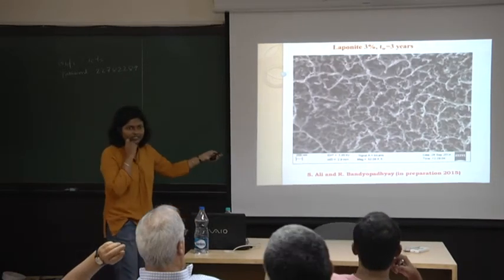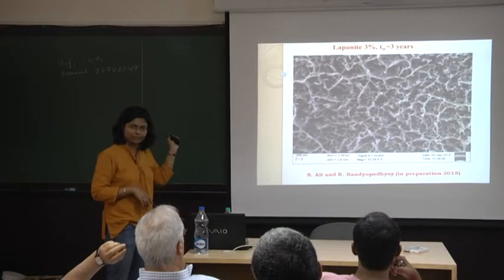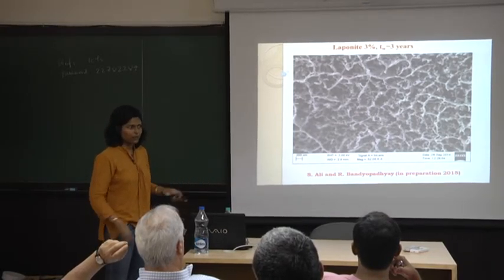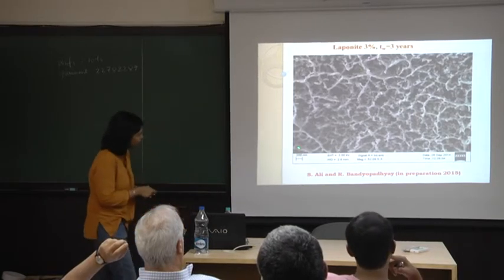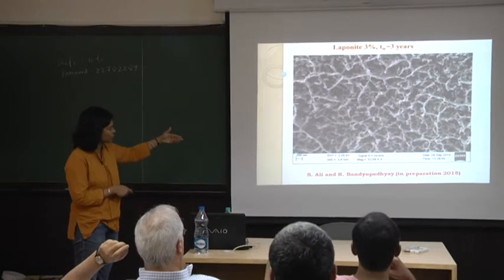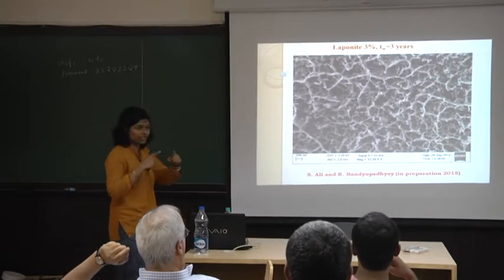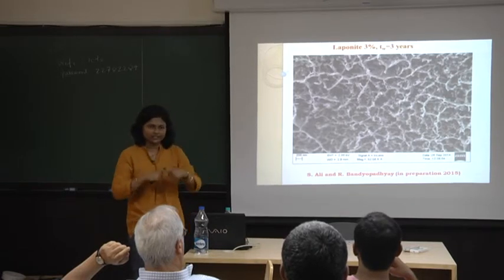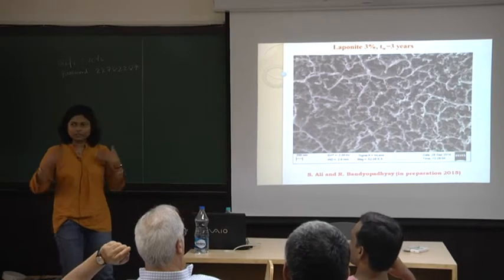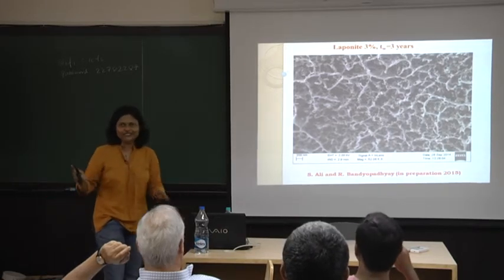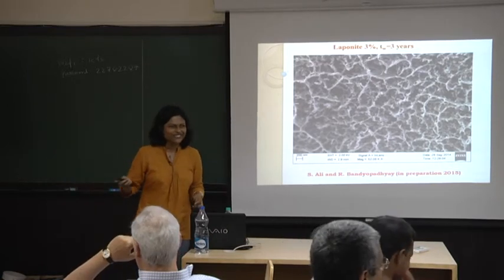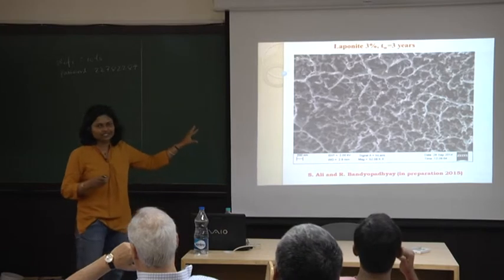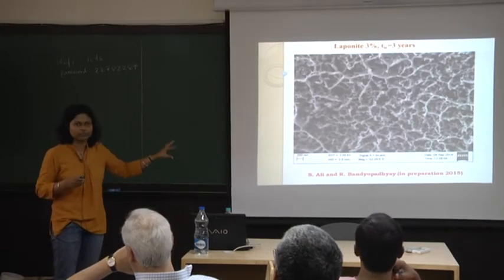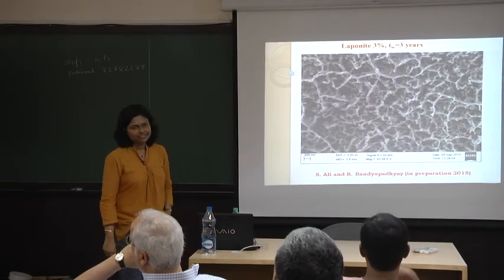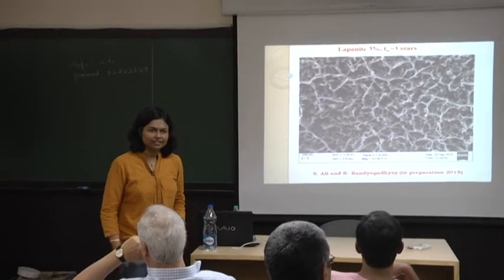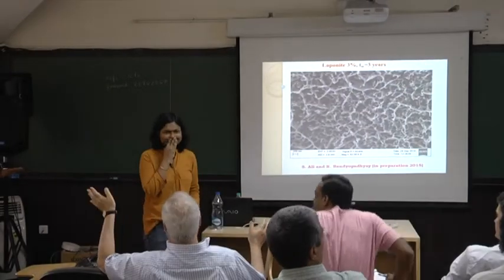It's a beautiful gel-like structure that we got for the same laponite suspension, but made 3 years ago. This is in a cryogenic scanning electron microscope, about 200 nanometers. If you look closely, you can see the edges of the particles touching the faces. Depending on the amount of salt you put in, things change, but I don't have time for that. So yes, attractive interactions are eventually very important in these systems. That was the punchline.